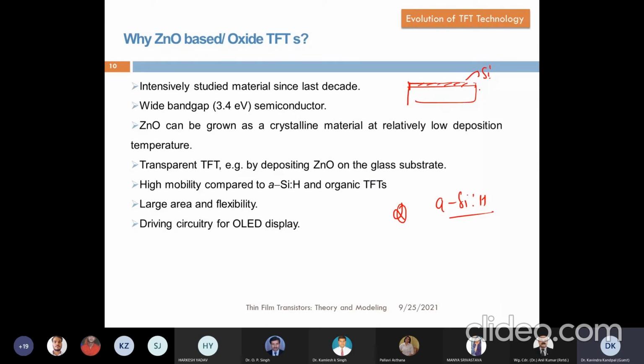For example, amorphous silicon will give you a mobility of 1 to 2 centimeters square per volt second, while single crystal silicon can give you almost 1480 centimeters square per volt second. So there is a huge difference in their performance, but amorphous silicon TFTs are going to be much cheaper, right? So at the very beginning, these were the amorphous silicon TFTs.